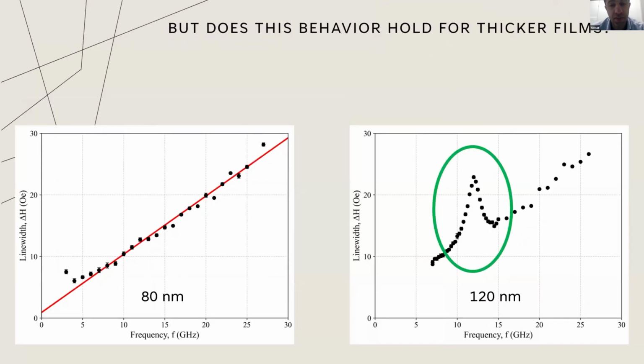But where is phonon? We talked about phonon, but where is phonon? The phonon shows up when we do FMR measurement for thicker films. So the plot at the right-hand side is our line width for 120 nanometer film. We observe a very clear and sharp bump. This bump is indicating that there is a new energy loss channel in this magnetic material.